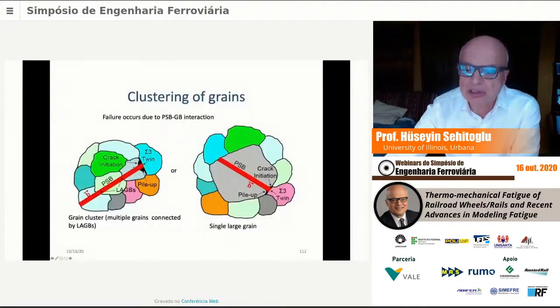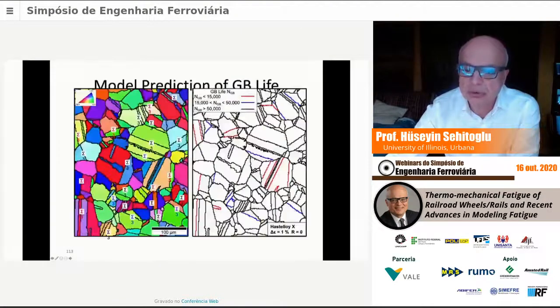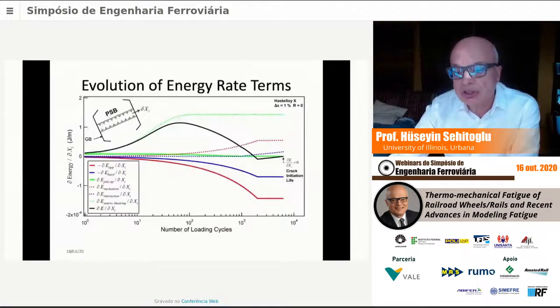But we're looking at clusters of grains like this. Two grains. We're looking at all possible combinations. Which one, whether this will give the shortest life, or whether this large grain surrounded by small grains gives the shortest life. So we do calculations for grains that have lower than 15,000 life, higher than 50,000 life. So we then, of course, look for the one that gives you the minimum life among all these simulations.